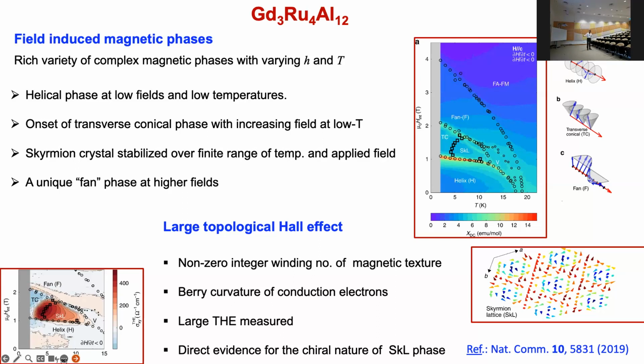At slightly higher temperatures, over a finite range of temperatures and field, you stabilize a skyrmion lattice, which is shown here. And right away, you will see that the size of the skyrmions is much smaller, only a few lattice sites wide. And then there is a unique fan phase at higher magnetic fields, which we will not get into. Our primary focus is on these small scale skyrmions. So that is determined from magnetic measurements.